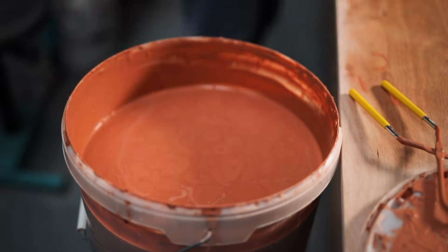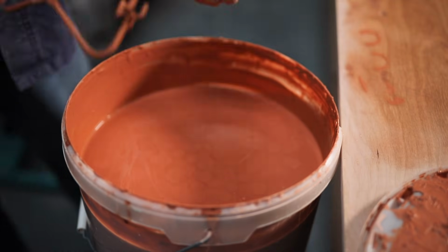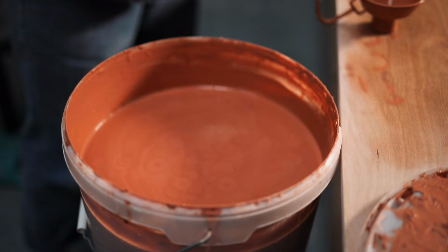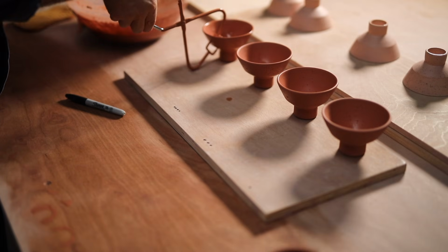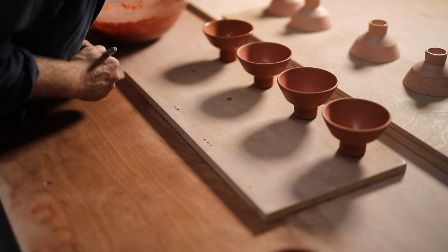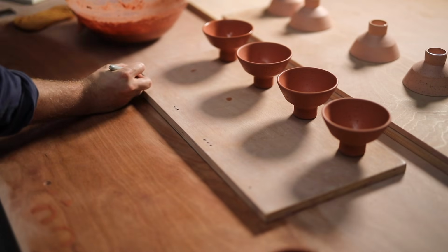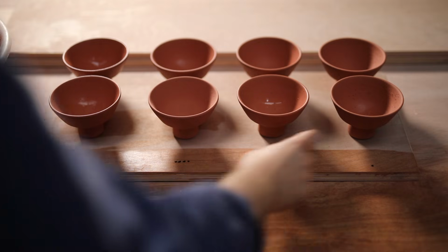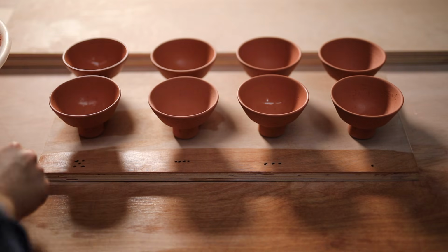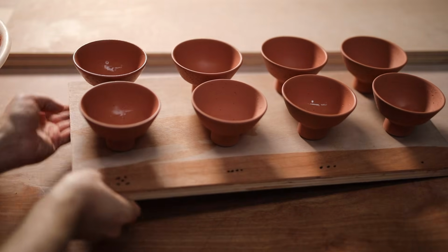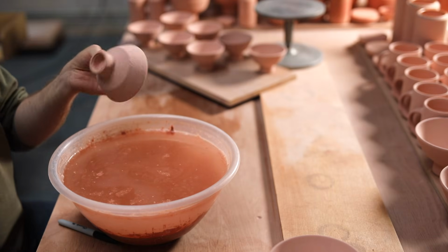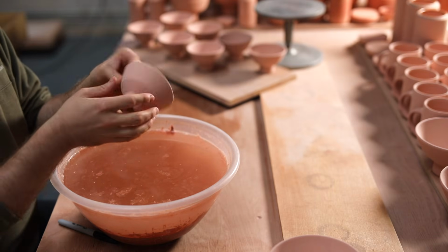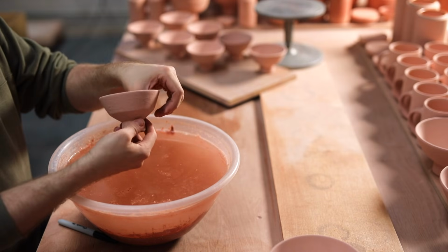For this step at least, the mixed in additions don't make any difference. The water is simply pulled into the porous body, and the raw materials particles, which are larger, simply adhere as a layer on the outside. The longer the pots are dipped for, the thicker this layer, but if you keep them submerged for too long, the pots can become oversaturated with water, meaning the glaze takes an awfully long time to dry, and it'll either just crack off at this stage, or there's a chance it'll crawl during the second firing, which is when the glaze begins to separate from itself.